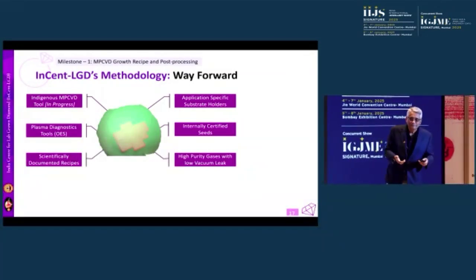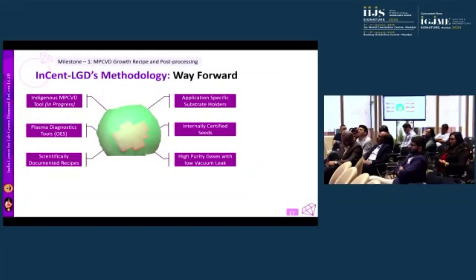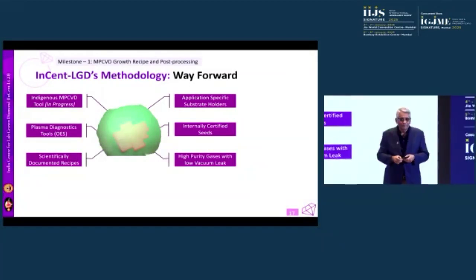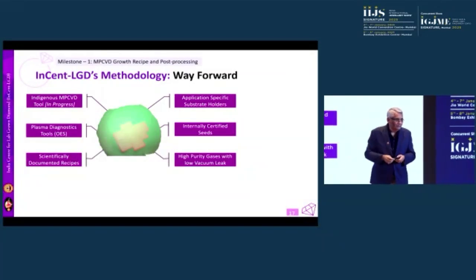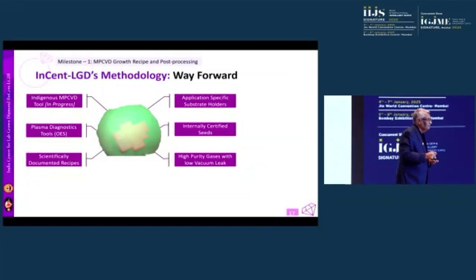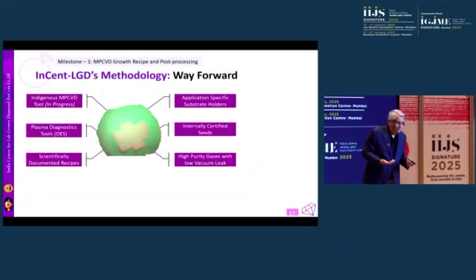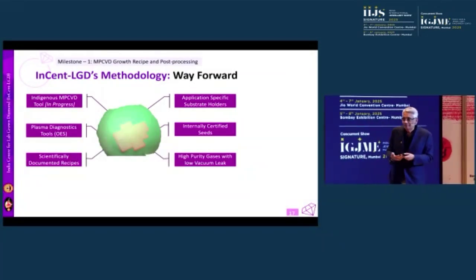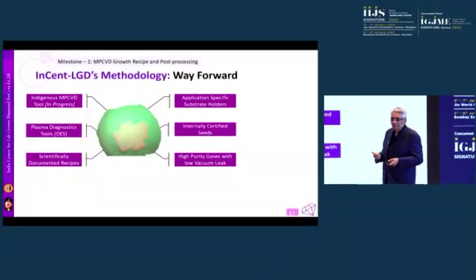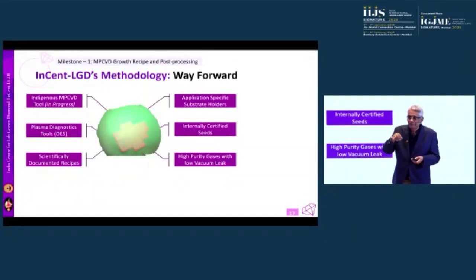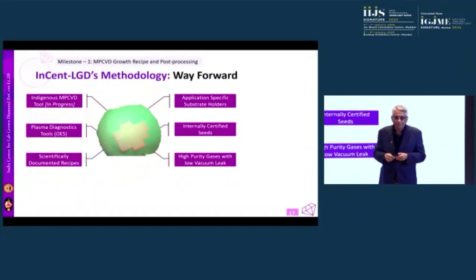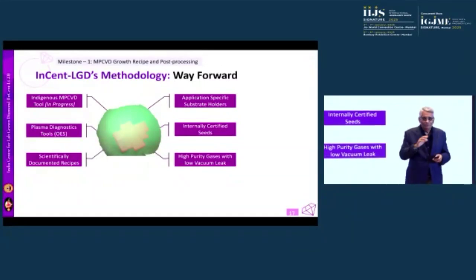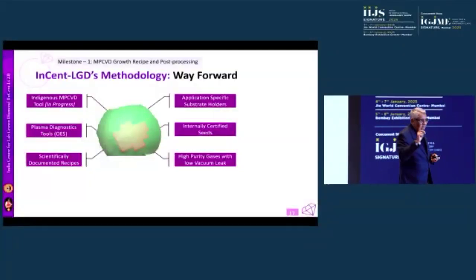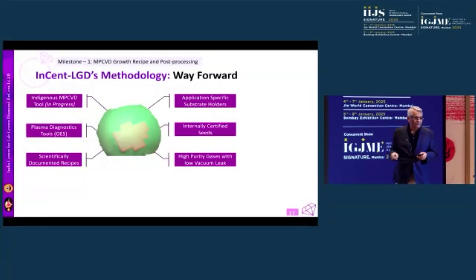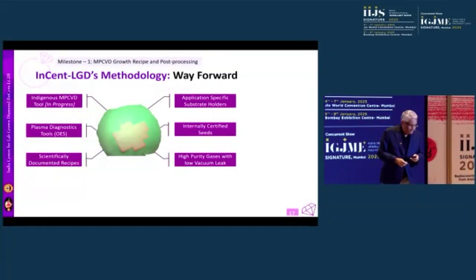What we have seen is people ask us that, look, I put so many seeds, and in order to enhance the growth, you also put a lot of nitrogen inside the growth chamber. That'll give you a quicker, big seed within a short time. But then you're putting so much nitrogen inside, it is brown colored, of course. And sometimes deep brown, sometimes it's black. And then you say, okay, we can treat them in HPHT, right? Put it in an HPHT unit for treatment, but then you're only dispersing those defects, you're not removing them. So the final quality will not be as good as what you're supposed to get to call it diamond, as a semiconductor grade diamond.